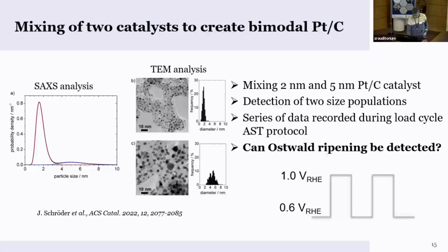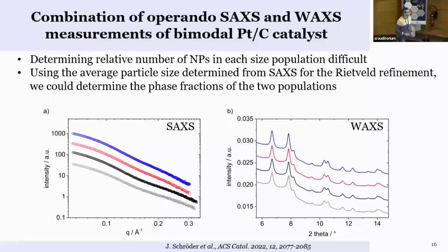Scattering. And then you apply such a degradation protocol and collect the data for small angle and wide angle scattering. And so what we find out is that you can easily distinguish the two populations, the average size. It's very easy to distinguish in the data, but if you want to look at the relative number of the population, so how many particles are in the small, how many are in the large population, and how that changes over time, it gets really tricky.